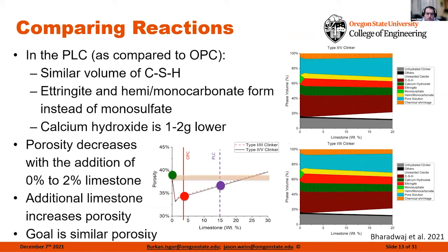We've also been able to use this type of approach to describe some of these new approaches, such as Portland limestone cement, where we can all of a sudden start to take people's fears away and say, really, what's happening when we add limestone into the system? Well, if we look at the right-hand side, what we can notice is if you add limestone, which is our x-axis, we look at the pore volumes and the phase volumes that are formed, on the y-axis. And what we'll notice is the unreacted cement, the limestone, the CSH, the calcium hydroxide shown here in green, all of these are relatively constant. We have pore fluid that's relatively constant, chemical shrinkage that's relatively constant. But what we notice is by adding limestone, we get this thing that maybe looks like a Central American flag here. And this thing is really the conversion of monosulfate to hemicarbonate and ettringite. And this actually stabilizes these phases and reduces the porosity in the system. And by reducing the porosity in the system, we can actually increase the strength.